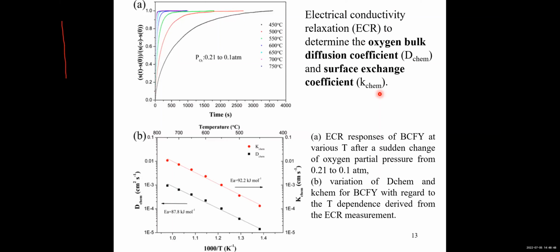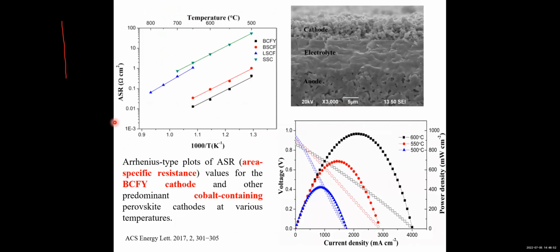And we also tested the area specific resistance of the different cathode materials. You can see this new material, the BCFY material, showed the lowest ASR compared with some other commonly used cathode materials. So it demonstrates that the material is better than other materials.